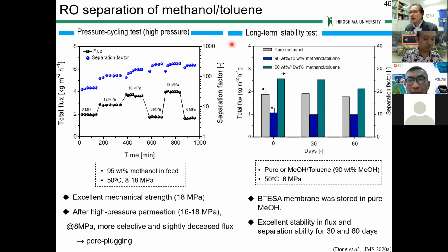The right side indicates the long-term stability test. Even after 60 days, kept immersed in the liquid phase, the membrane still shows high performance. It's also similar performance to the beginning. So we believe this membrane has good long-term stability.